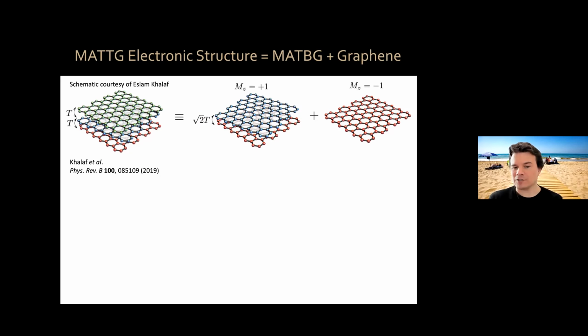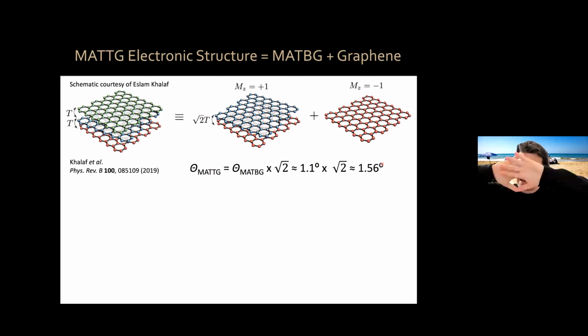Now, remember I told you earlier that the interlayer tunneling determines the magic angle. Because of this square root of 2, the magic angle for twisted trilayer graphene happens to be the one for twisted bilayer graphene times square root of 2. So it's 1.1 degrees times square root of 2, 1.56 degrees. That means that because the angle is a little bit larger, the moiré wavelength is now smaller. It's about 9 nanometers instead of 13 nanometers, as I told you earlier for the bilayer case.